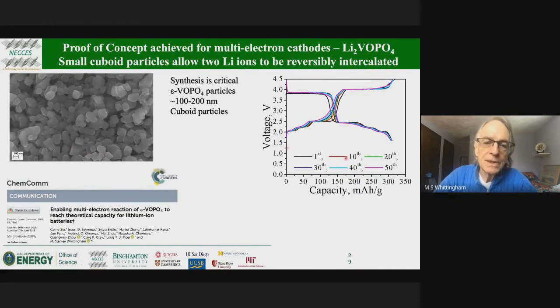So this is what these crystallites look like, little cuboids. They're about 100 to 200 nanometers on an edge. Extremely uniform. You'll see this is the advantage of these solvothermal, hydrothermal techniques. And the electrochemistry of this worked very well. Here is the redox couple vanadium 5 to vanadium 4 at about 4 volts. And here's vanadium 4 to vanadium 3 at just over between 2 and 2.5 volts.